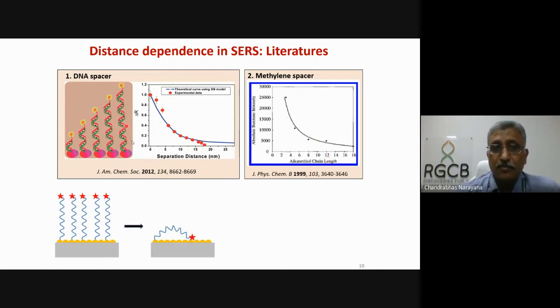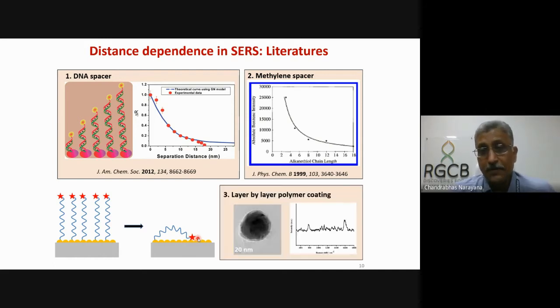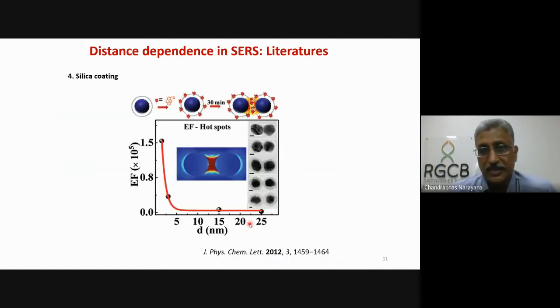But the problem with these two spacers is that they are not rigid. They cannot be stiffly standing. They can actually buckle, and as the length increases, the buckling will be more. Hence, you may not be actually measuring the right distances. So people did another experiment where they put a polymer coating on top of this and tried to measure the Raman of the polymer. But as you know, polymer also doesn't give you a clear idea of your extent.